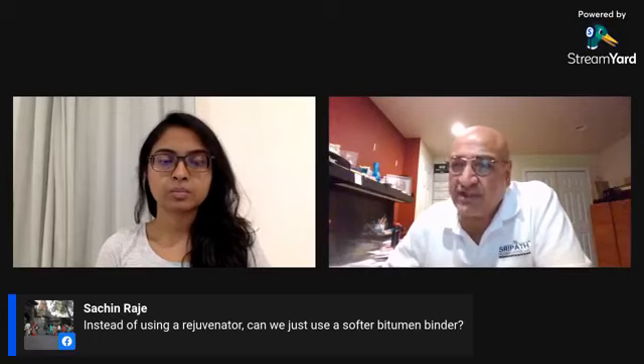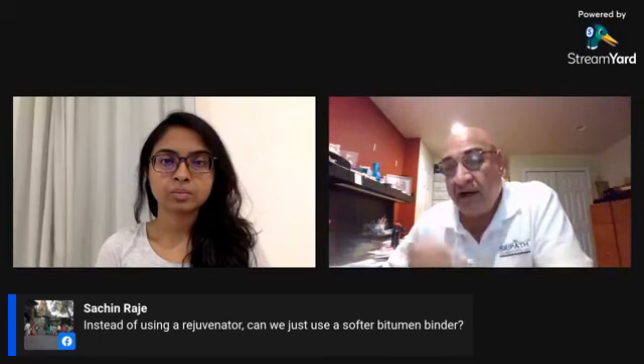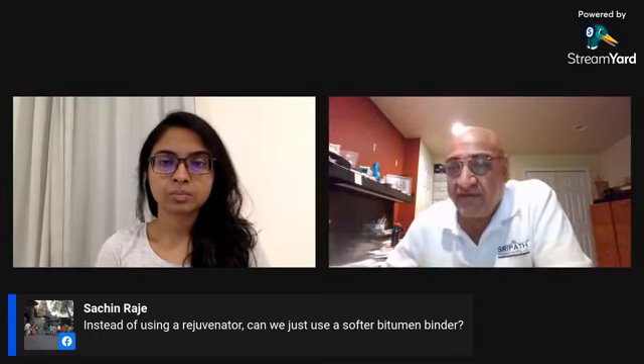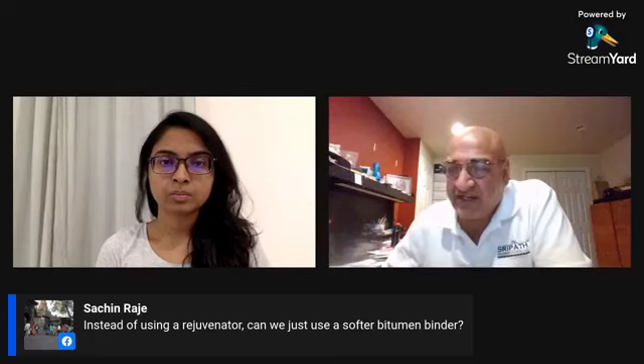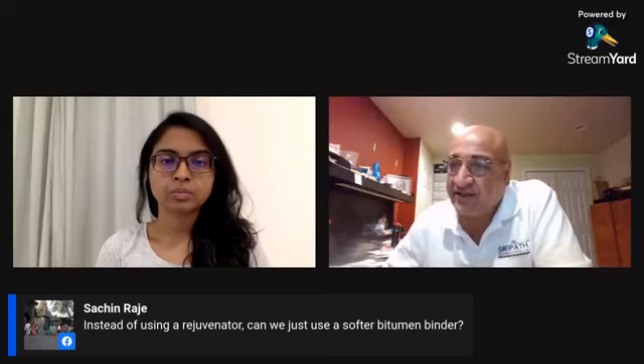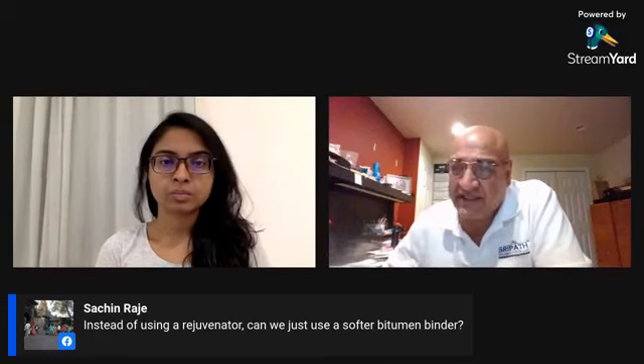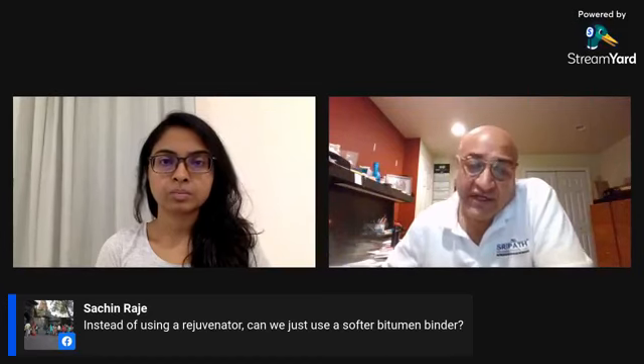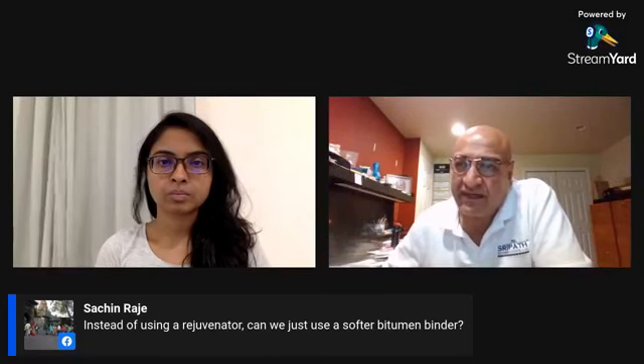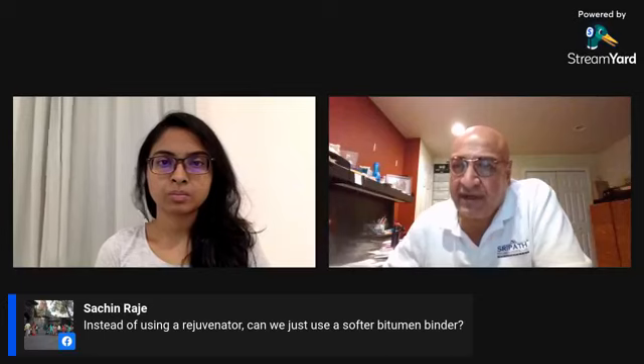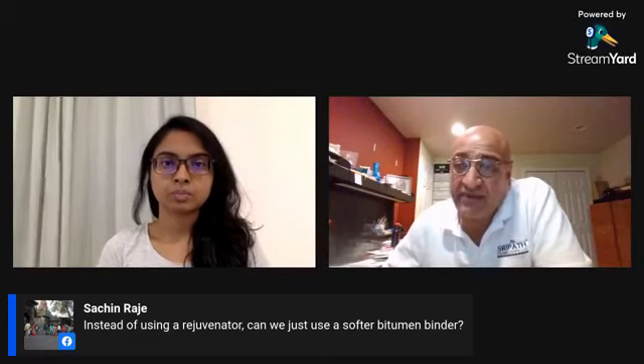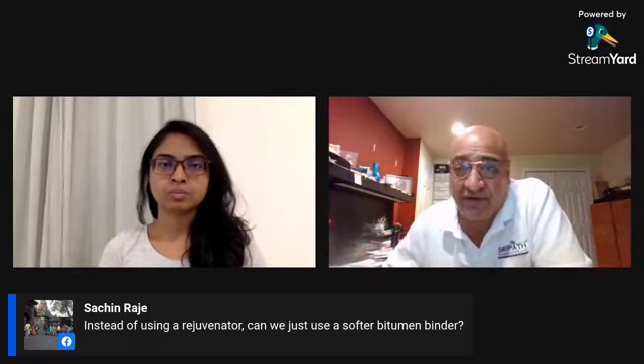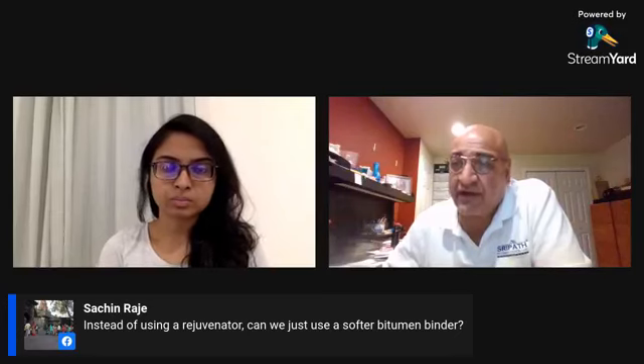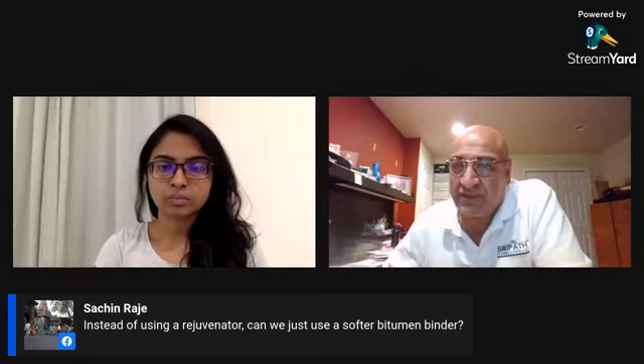Second, dosage efficiency of these softer binders is not nearly as good, and this has a direct bearing on economics. As I mentioned during the talk, for something like a 50% ABR mix, you use maybe 1 kilogram of our rejuvenator. It's simply not possible with softer bitumens.